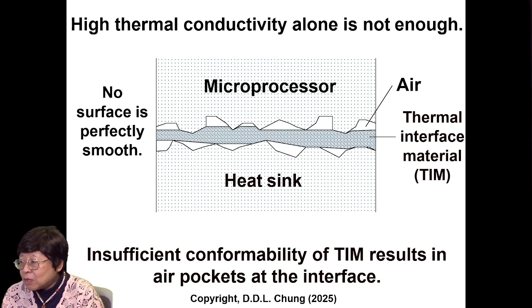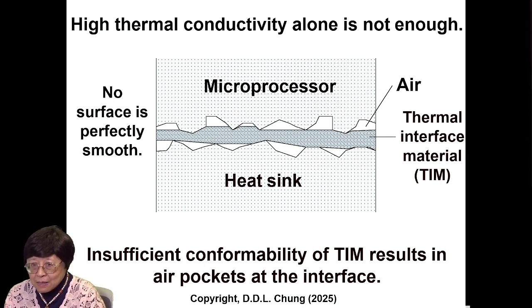Now, high thermal conductivity for the thermal interface material alone is not enough. The reason is no surface is perfectly smooth. So you always have some ups and downs, so some air pockets at the interface. And so the thermal interface material better enter all these little valleys and displace the air out. If you have insufficient conformability of the TIM, you would have air pockets left at the interface, and air is a thermal insulator.